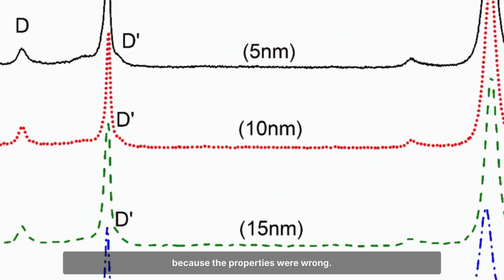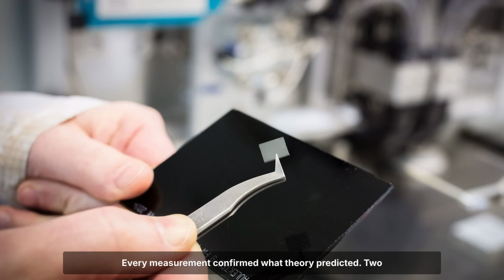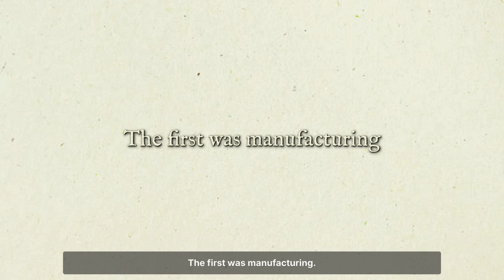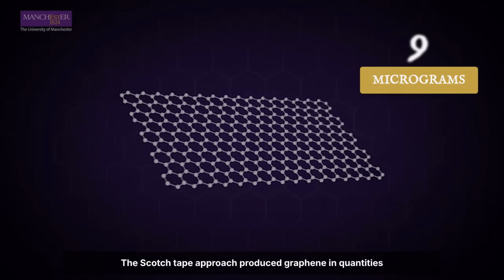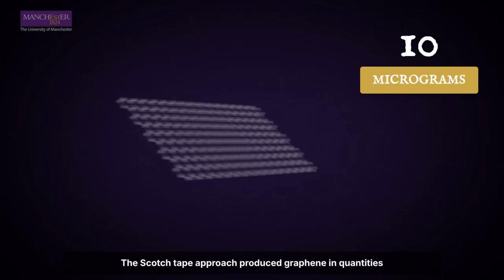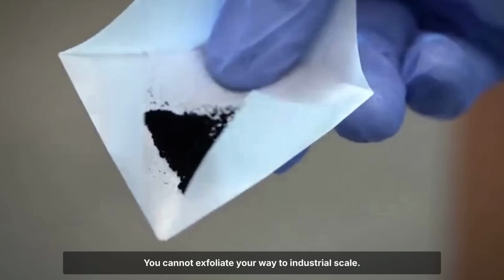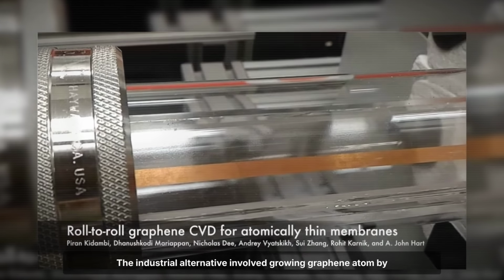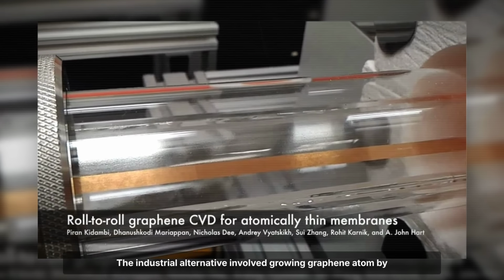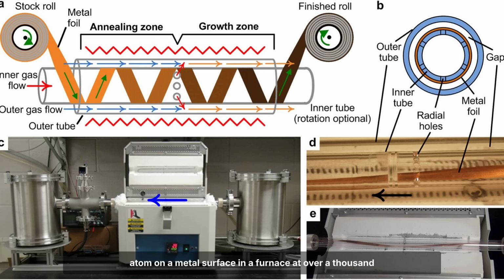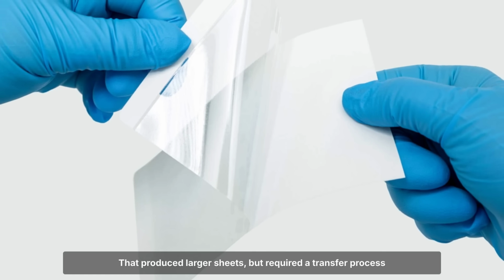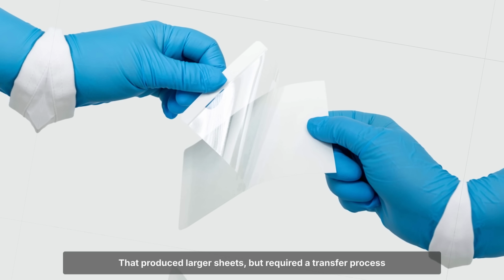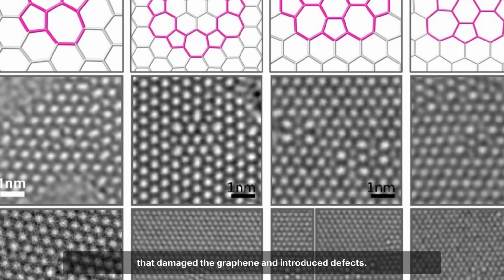Not because the properties were wrong, every measurement confirmed what theory predicted. Two things killed it, both mundane, neither mentioned in a single press release. The first was manufacturing. The Scotch tape approach produced graphene in quantities measured in micrograms. You cannot exfoliate your way to industrial scale. The industrial alternative involved growing graphene atom by atom on a metal surface in a furnace at over 1,000 degrees Celsius. That produced larger sheets but required a transfer process that damaged the graphene and introduced defects.